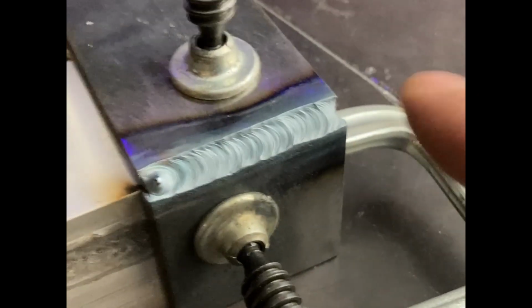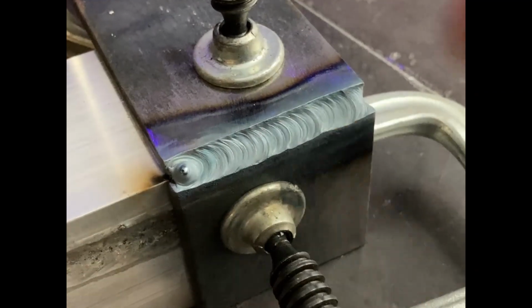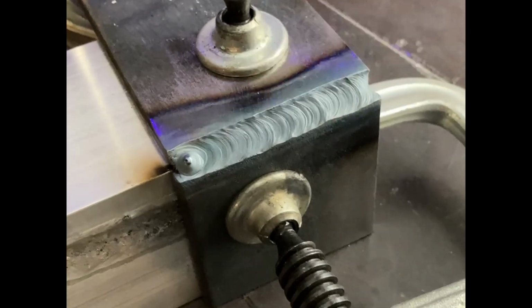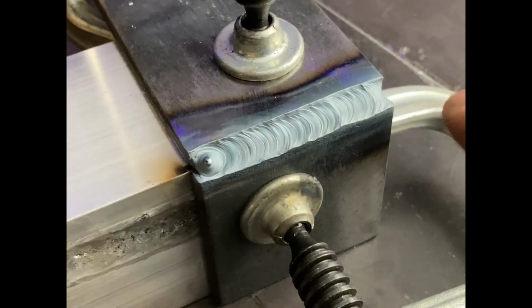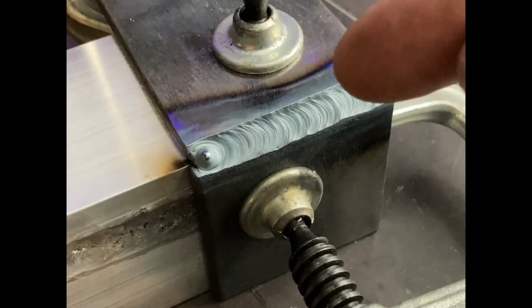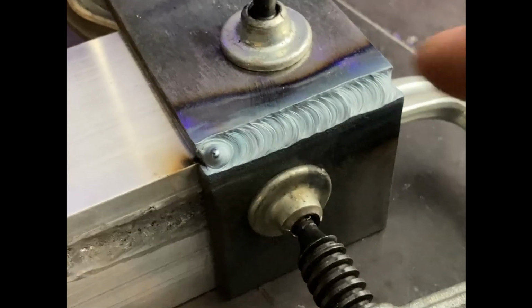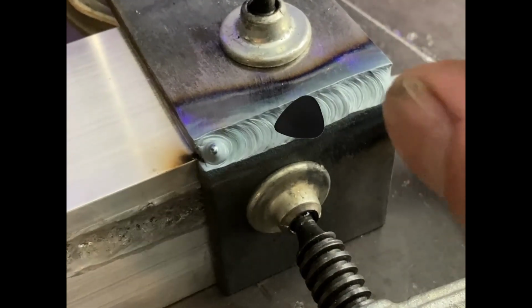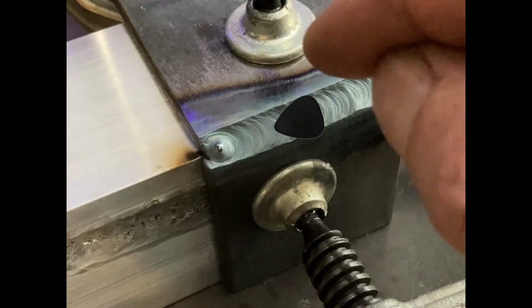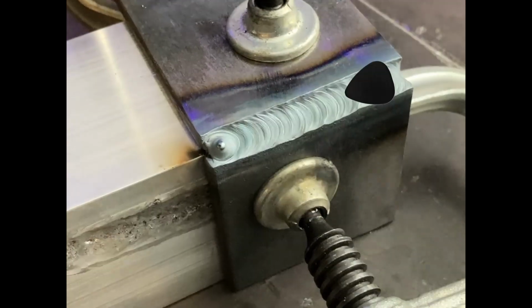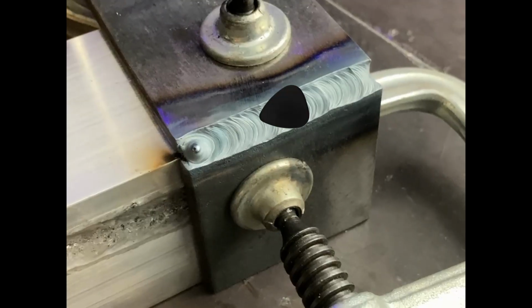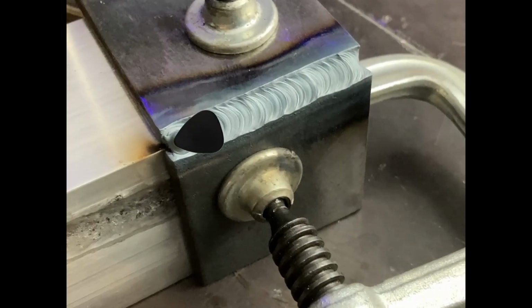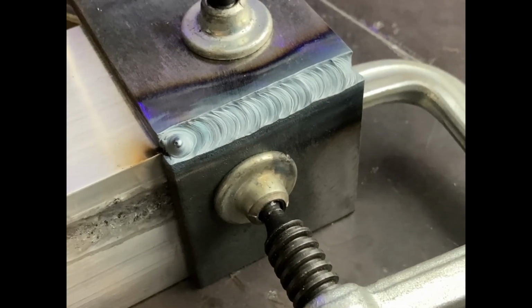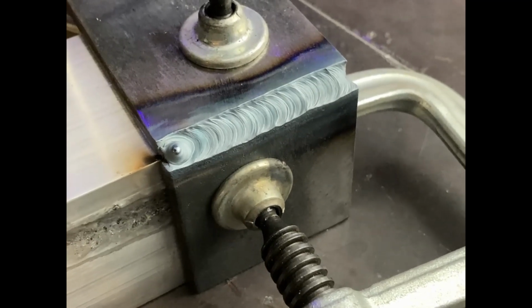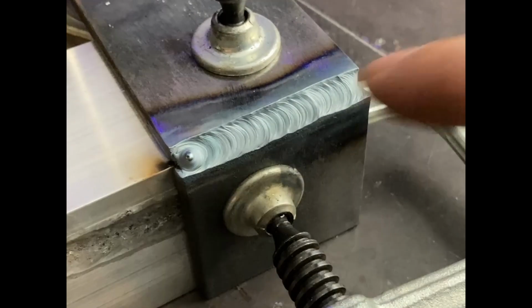All right, so here's a picture of that weld. I made this one in a single pass from this side to this side, moving in a right to left direction using a forehand technique. I like to go just a little bit more than recommended. It gets the tungsten out there so I can see it. And I start to look in this type of joint for a puddle that looks like a teardrop, slightly elongated to the front. I call it a guitar pick. Once you see that guitar pick happening, you know you're ready to just start flying. And if you lose the guitar pick, you've either lost the puddle, you've used too much amperage, or you've got the wrong angle. So make sure you pay attention to that.